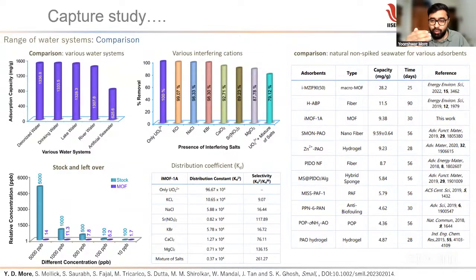In seawater, to adsorb or take out any cation, the biggest competition is from potassium and sodium, because they are in the highest amount in the seawater. Then the third concentration is calcium. And there are a few other cations like strontium, magnesium, titanium, and vanadium. They are the competitors of uranium. If you use the uranium selective adsorbent in a bulk seawater system, along with uranium, titanium, strontium, and vanadium are going to interfere in a very high amount, because they interfere with the selectivity due to similar molecular geometry or ionic size.